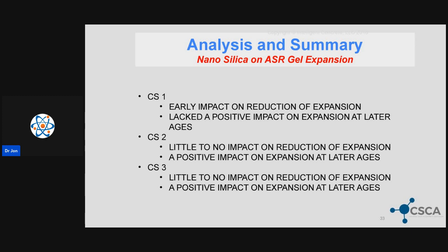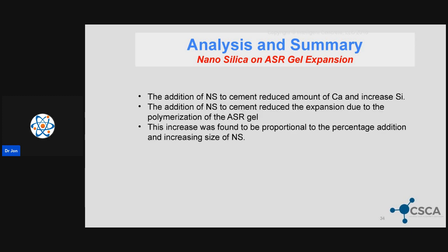So we saw the smallest particle size had an earlier impact on the reduction of expansion, but it lacked a positive impact on expansion at later ages, and that means the growth over time. With CS2, there was little to no impact on reduction of expansion, but there was immediate expansion. But over the later ages, obviously there was more positive effect as we added more. And the same thing can be said for that largest particle distribution, that 45 to 47 nanometers.